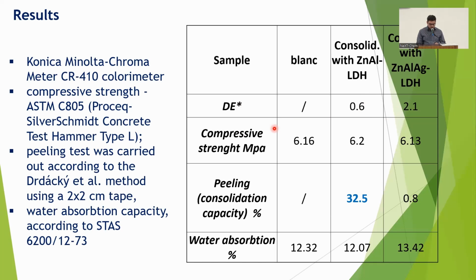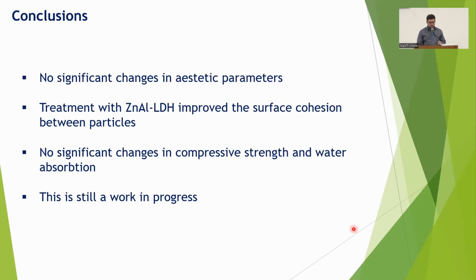We tested the compressive strength of the treated bricks. We also did not observe much effect in improving the bond between grains of material. The peeling test showed some interesting results in the case of the zinc aluminum layered double hydroxide. The adhesion between the grains at the surface of the brick was improved considerably. And also the water absorption was not changed dramatically. In conclusion, the treatment with the consolidants did not change the aesthetic parameters of the material, but in the case of zinc aluminum layered double hydroxide, it improved the surface cohesion between grains, and no significant change in compressive strength and water absorption was observed.